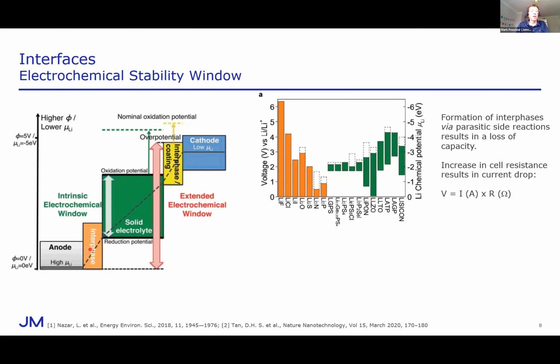Anyway, as a consequence, when these things are run outside of their windows of stability, or indeed just under inherent conditions, open circuit voltage contact with the lithium metal, you can make these interphases, and these tend to be these binary compounds that represent the final decomposition products of these electrolyte materials. And problems really occur when these interphase materials are either ionically resistive, which would result in the increase in resistance of the cell, or they're electronically conductive, which results in the fast decomposition of your electrolyte and cell failure.